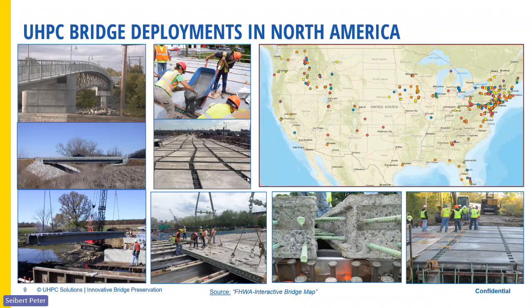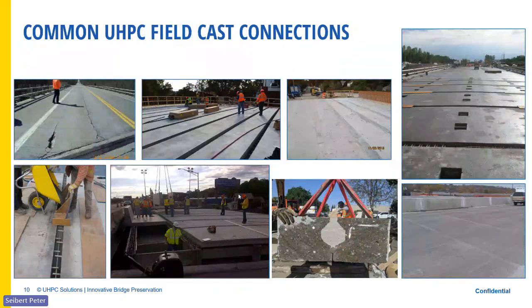When you would test it, you can make very small connections, as you can see here. They're usually 4 to 6 inches wide. The rebars don't have to overlap because the UHPC can take all the strength in the connection. Here's a couple other applications. You can see precast box girders, and this is what I was talking about, that the rebars don't have to overlap. You can make very nice, efficient connections. Here's the same thing, a saw cut between the precast deck panels, and here's the UHPC in there. It's very good for accelerated bridge construction.